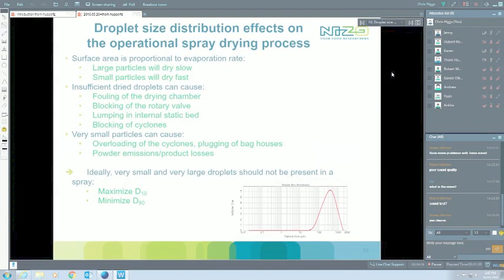Because as we said, droplet size distribution during atomization in the dryer is really one of the key operational aspects. When we look at the droplets themselves and the drying, surface area is really proportional to evaporation rate, how quickly droplets will dry. Large particles are going to dry slowly. Small particles are going to dry fast and sometimes extremely fast. On the one hand, of course, we want to avoid poorly dried droplets. They're going to be fouling the drying chamber, blocking rotary valves. They can give us a lot of lumping in the internal bed. We can get a lot of blocking of cyclones as well if we don't dry well enough.